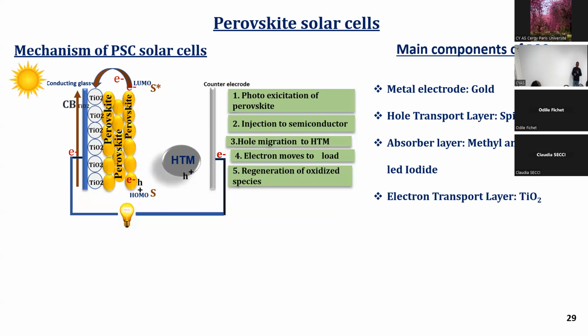In photoexcitation of the dye, or of the perovskite, an electron moves from the ground state to the excited state. From the excited state, the electron is transferred to the conduction band of TiO2 and reaches the FTO. After the electron moves out, the hole is transferred to the hole transport material. After the electron moves to the counter electrode, the hole transport material captures the electron from the counter electrode. So regeneration of this process is done, and the hole is transferred from the perovskite to the hole transport material.